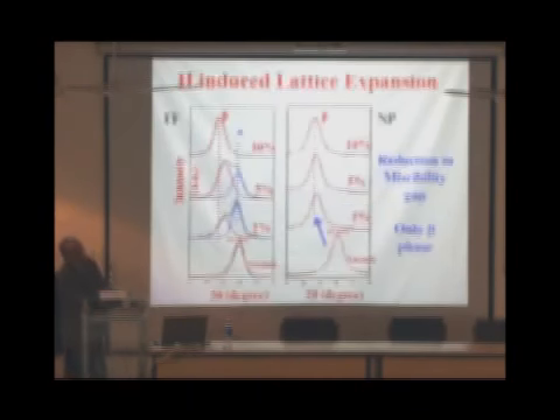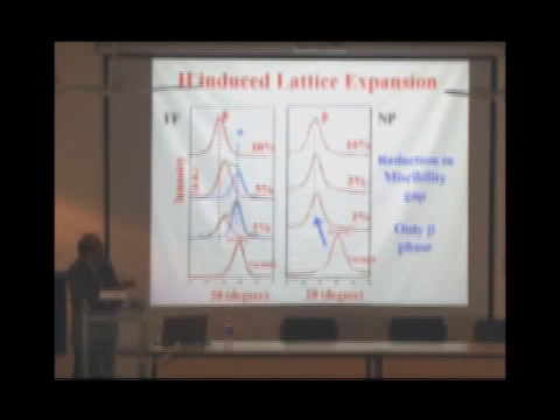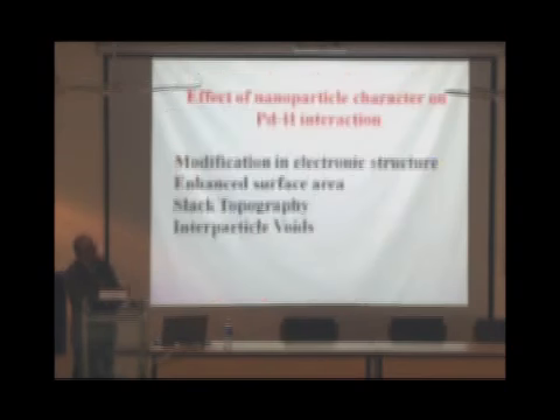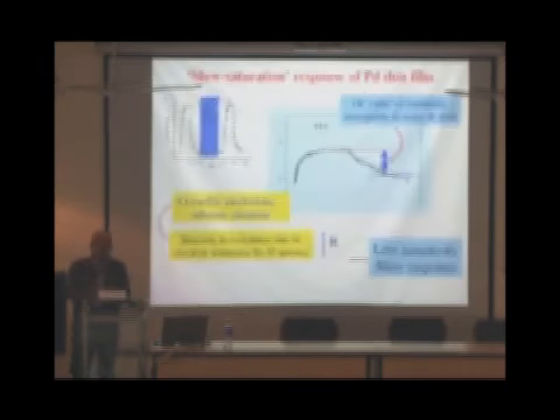So what we observed is that in the case of nanoparticles, because of the presence of these defects or these gaps, if we do X-ray diffraction, which tells us the structure, in the case of thin films, we can say that even up to 2% hydrogen or 5% hydrogen, you can still see the alpha phase of palladium. Not much hydrogen is going in. You have the low concentration phase alpha and also the high concentration phase beta. But in the case of nanoparticles, even at 2%, we have only the beta phase. So because of all the effects which I discussed, more hydrogen can go into the palladium, even at smaller concentrations of hydrogen.